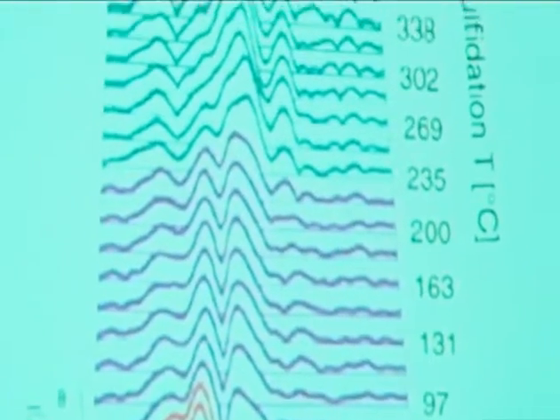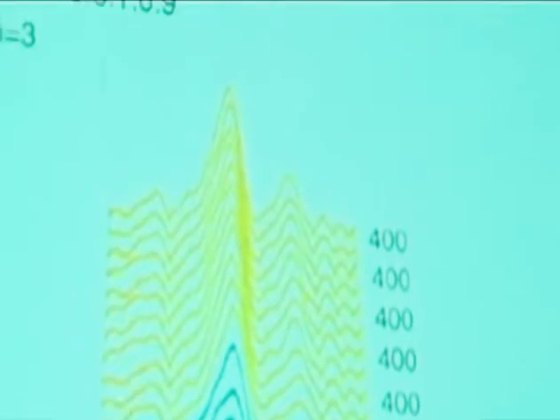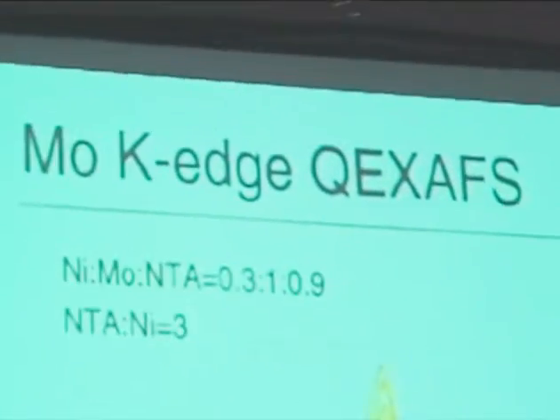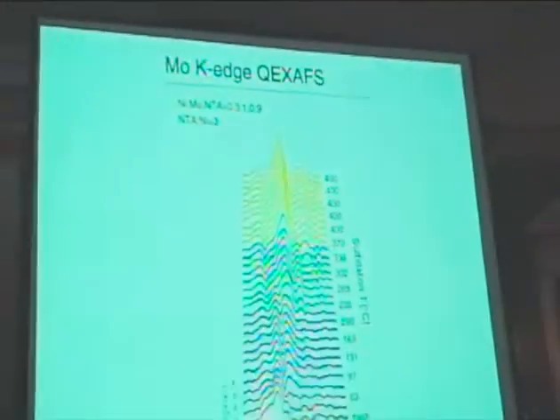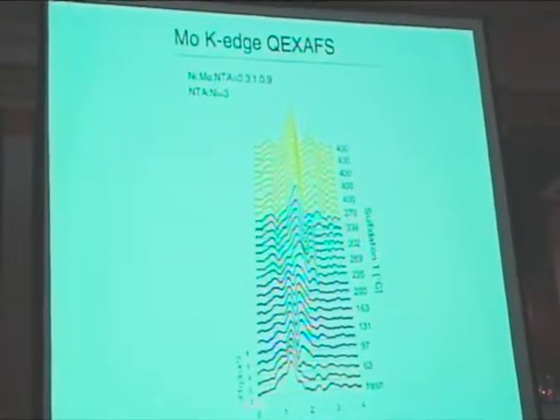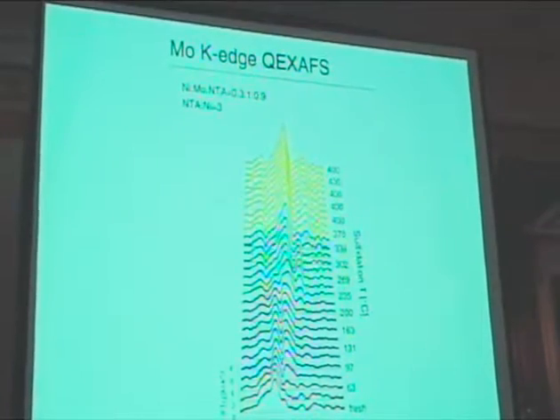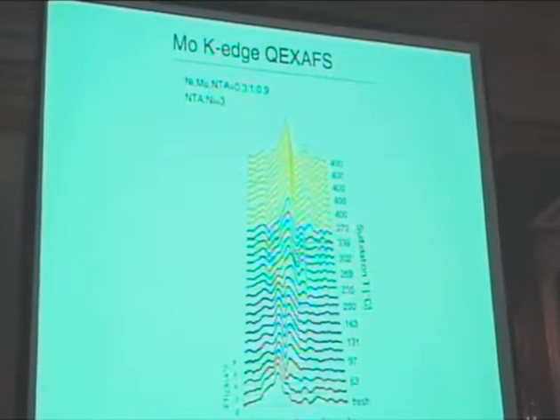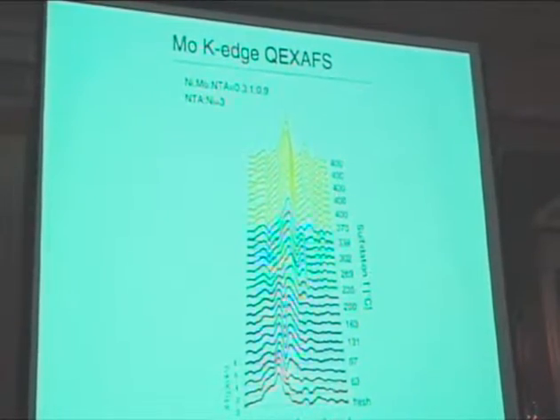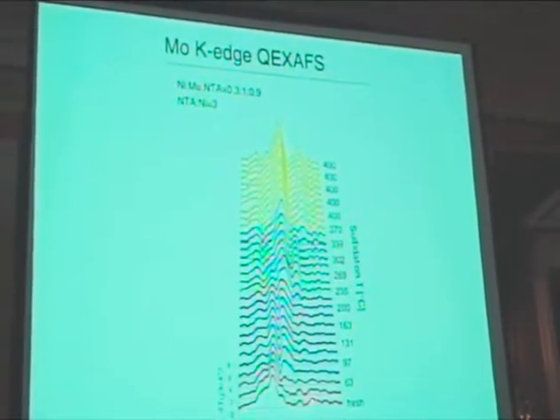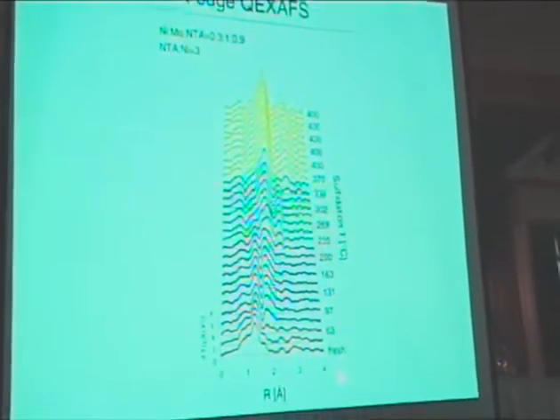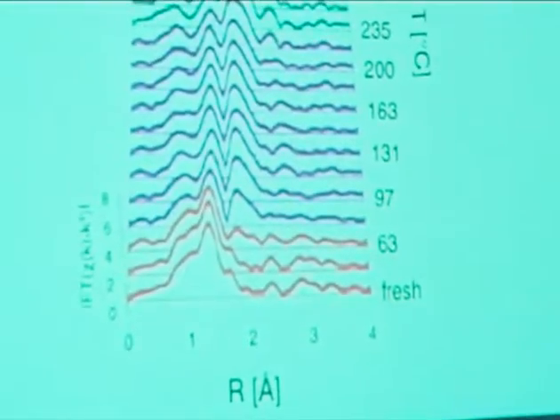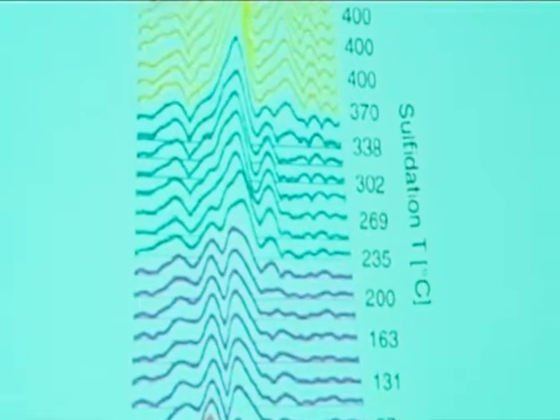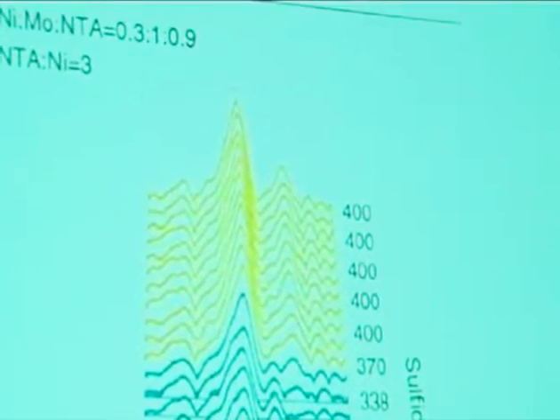So here you see many spectra, which we do on the fly. In a couple of seconds we measure one spectrum, and we add 4 of them. That means one spectrum you see here is an average of 4, so by the time we go to the next, the temperature has already changed somewhat. But if you do it slow enough that you are not in the danger zone where you see the big changes, then you can do it this way. So here is the temperature in Celsius: room temperature, fresh catalyst, going up all the way to 400, and from here on we keep the temperature at 400. And what you see is a Fourier transform spectrum.